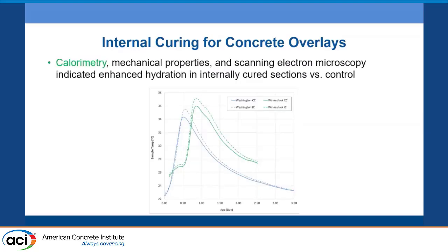So some of the testing that the team did at the time, they monitored calorimetry, and you see two sets of two different curves here. During the same year, the team also did a sister project where they used lightweight fine aggregate on a full-depth conventional concrete pavement, so they were able to look at both the internal curing of both an overlay and a conventional concrete pavement on another county highway. The dashed lines indicate the internal curing sections. The solid lines are the control sections.